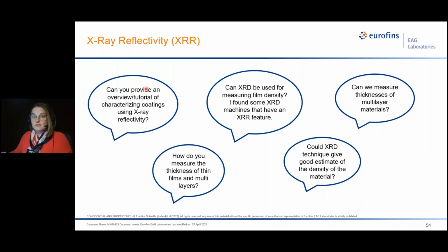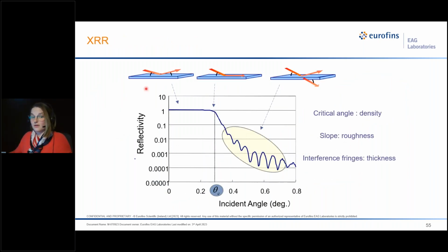So X-ray reflectivity is something you can also do on a diffractometer. Technically, it's not diffraction, but it's still a very important thin film characterization technique because you can get 3 very important variables about your thin films from XRR data. So we're scanning from 0 to maybe 2-3 degrees at most when we are doing this kind of scan. At the beginning, all of your x-rays are going to be reflected. So we see this flat plateau in the data. When we see this sharp drop, we call this the critical angle. And this is when the x-rays start to penetrate into the sample.